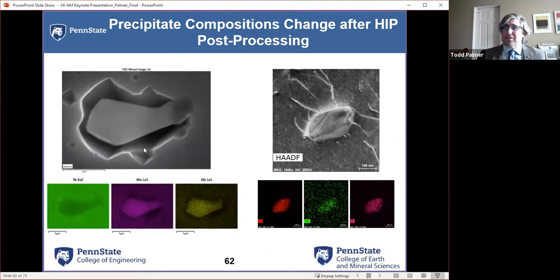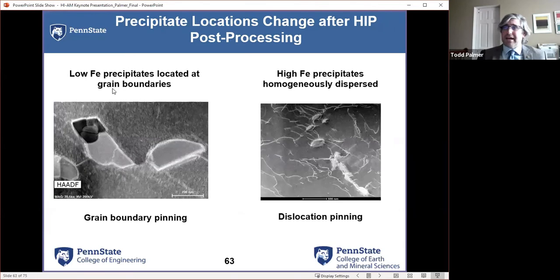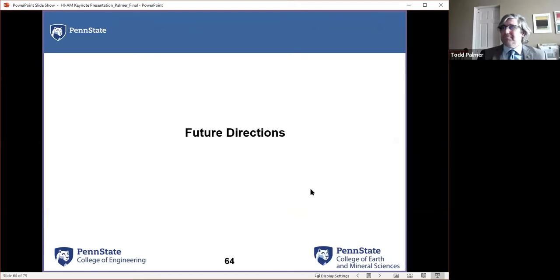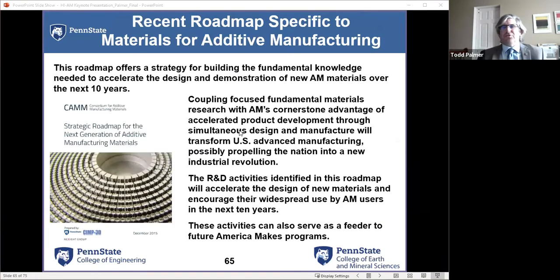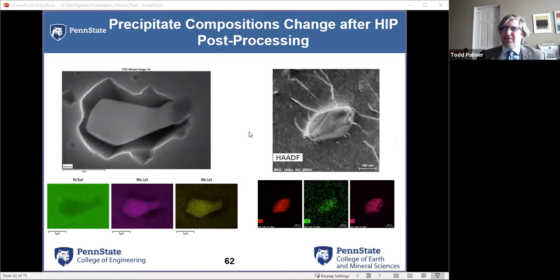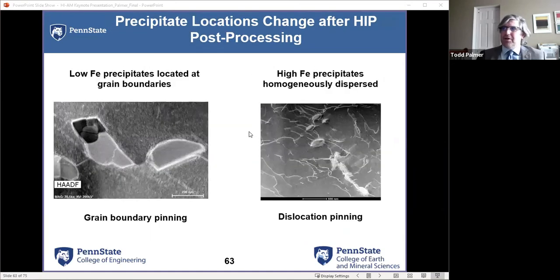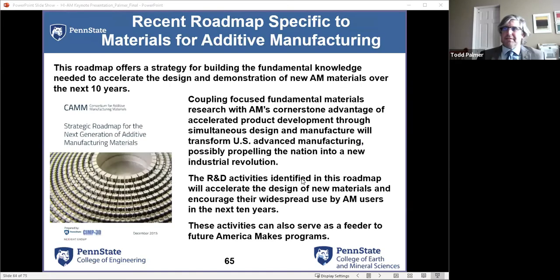Now, the precipitate morphologies ended up being different. If we started looking at them, the low iron tended to be pinned on the grain boundaries. The high iron tended to produce a little more dislocation pinning. So let's get into the future directions. I have a lot more on this, but I do want to cut it short. What we see here is that each of these precipitates is different. The change in iron content actually impacted the precipitates that were present in the materials.